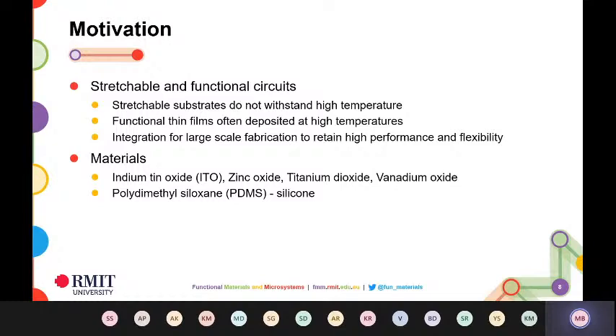materials are usually deposited at very high temperatures. And generally, oxides are extremely brittle. So you don't really stretch them or flex them. You essentially end up getting cracks. And so they're not going to really work under levels of strain. On the other hand, you have stretchable materials which don't really withstand very high temperatures. So we wanted to see if we can come up with some kind of a process by which we can actually combine stretchable materials, and when I say stretchable materials, I mean materials like PDMS, which is silicone rubber, with functional oxide materials and use them for various applications.